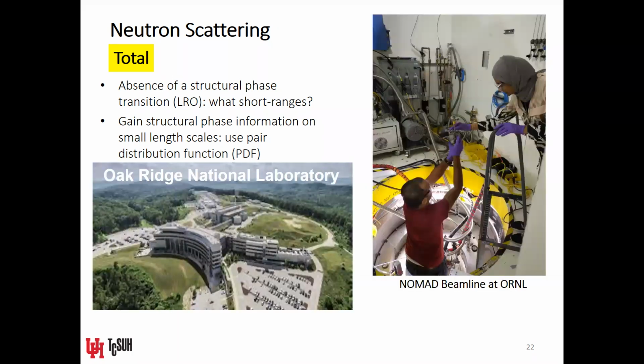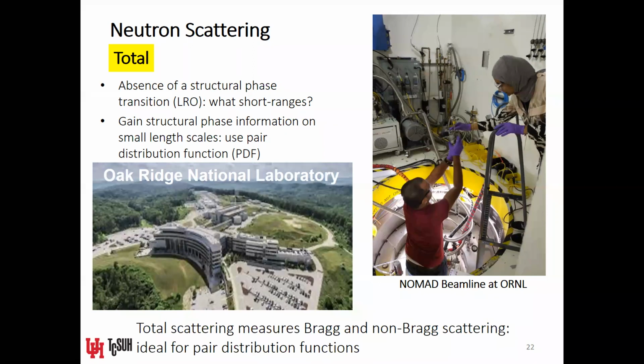So what we did was we used a technique known as pair distribution function. In this case, we applied neutrons, and pair distribution function enables you to understand the structural arrangement of materials on a local or small scale. And importantly, you don't have to have a single crystal sample. Pair distribution function can be used for the type of samples we had, which were, as I mentioned earlier, powder samples.